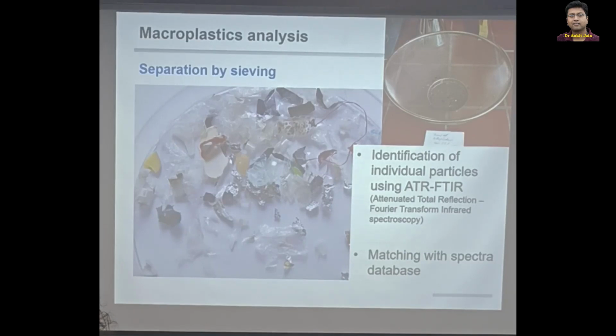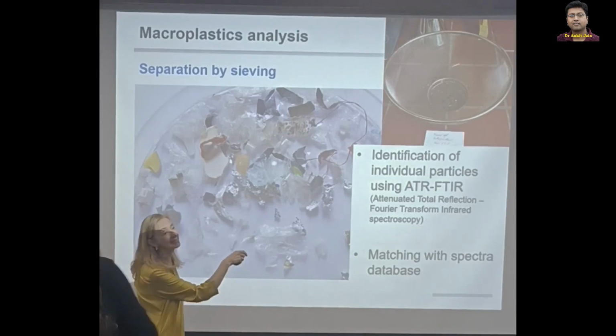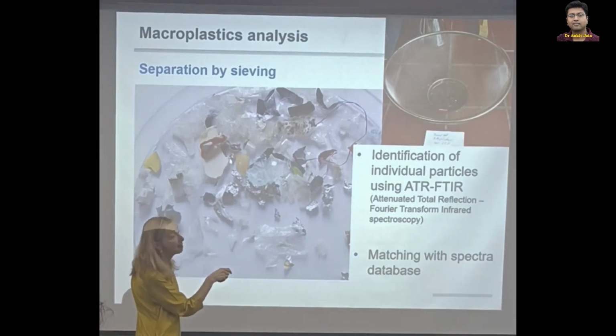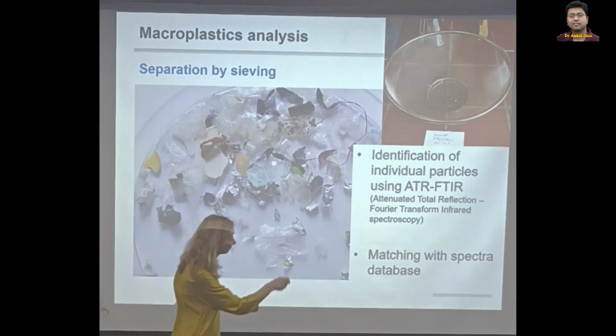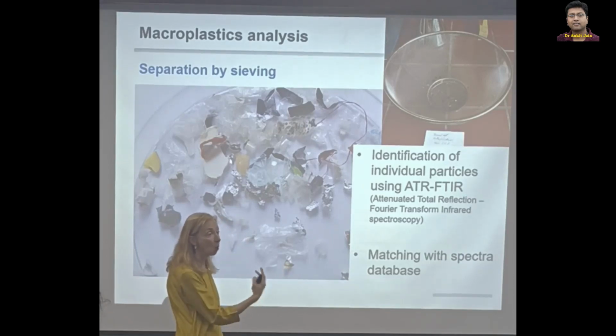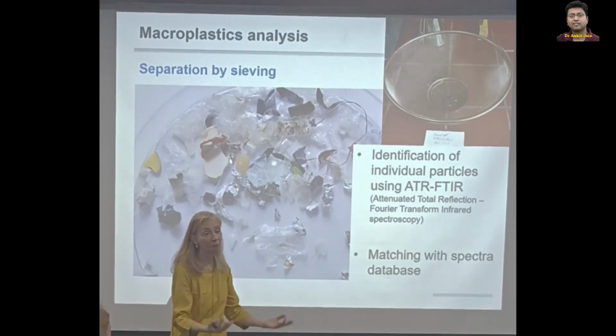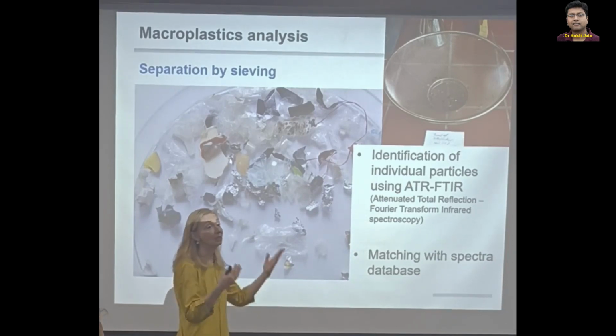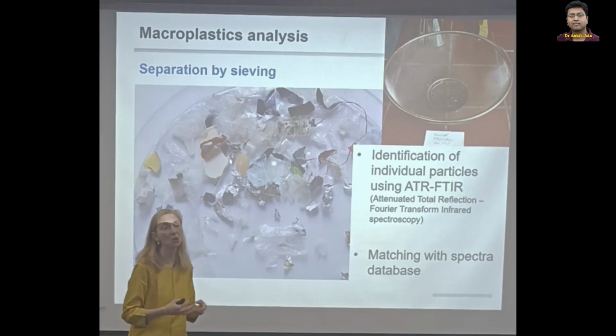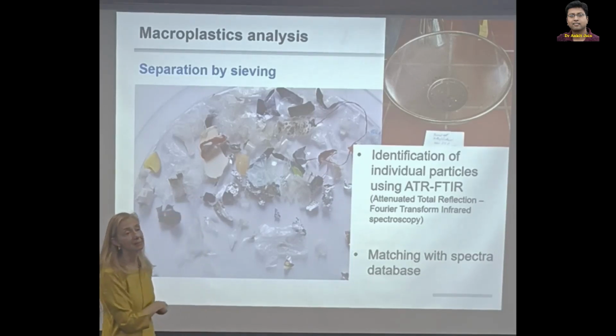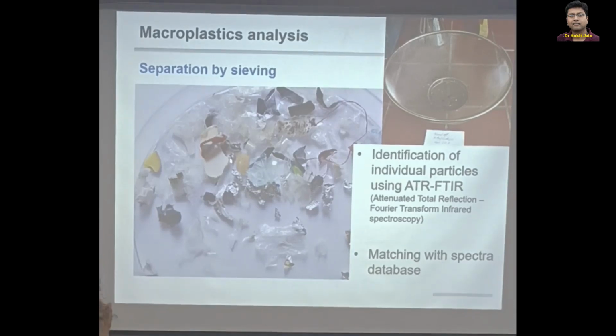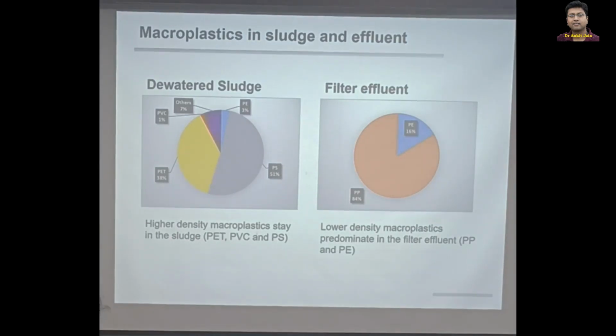How did we collect these plastics? We filter it, water or sludge, through this sieve. And like this, you see, we were able to collect the macroplastics. Then the composition of these macroplastics was analyzed by infrared spectroscopy, and we analyzed the amount and the mass of the macroplastics. But in this case, to separate them was easy because they were very big and we could use this big sieve. Then we weighed the plastics, we counted the number of particles, we studied the composition using the infrared spectroscopy. And here are only some examples.